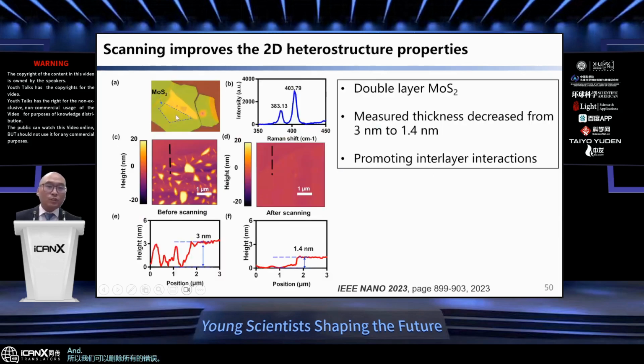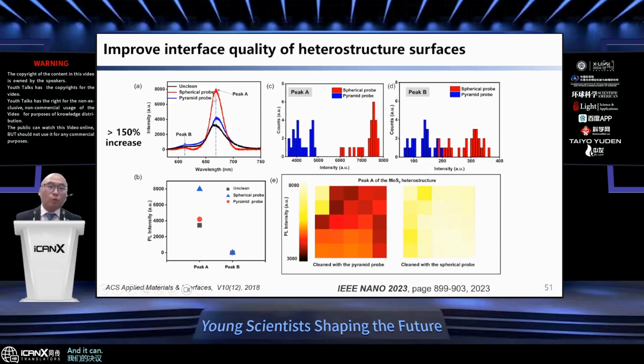This is the 2D full bilayer MoS2 material deposited on hBN. If you don't do this treatment, there are bubbles there. If you measure the thickness of this 2D material, it gives you 3 nanometers. But after scanning, you can get a very smooth surface, removing the bubbles and contaminants. You can precisely get a 1.4 nanometer thickness, and it can promote the photoluminescence property of 2D materials by more than 150 times.